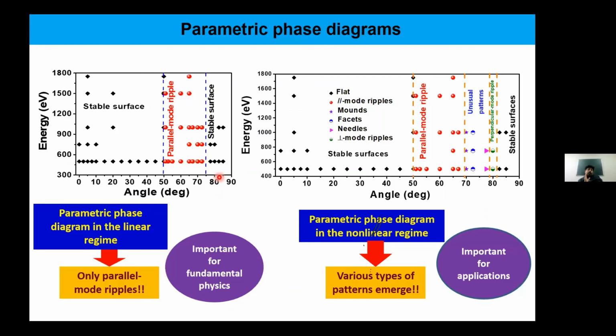These are at lower ion fluences, so that's why these are in the linear region. Only parallel mode ripples were formed. Remember, these facets that we saw earlier were an outcome at 72.5 degrees or so in the very early stage. I showed that result, and that is an outcome of the nonlinear region, when we go to very high fluences. Otherwise, in all angular windows, either we saw parallel mode ripples or no other patterns. That's in the linear regime.